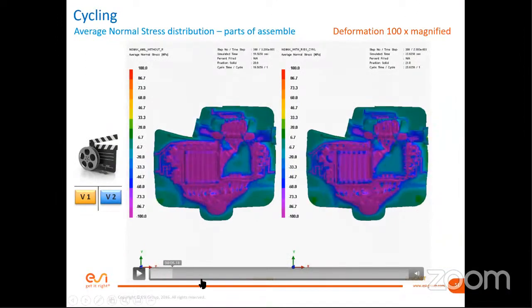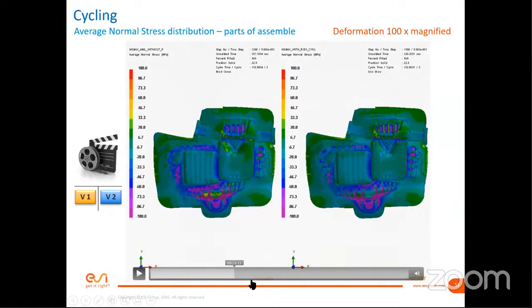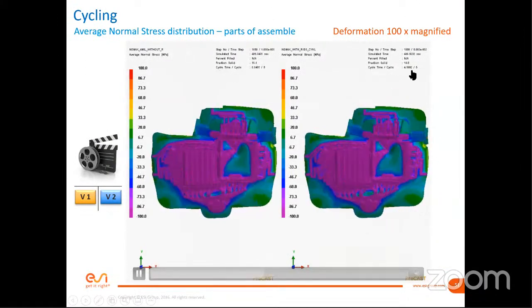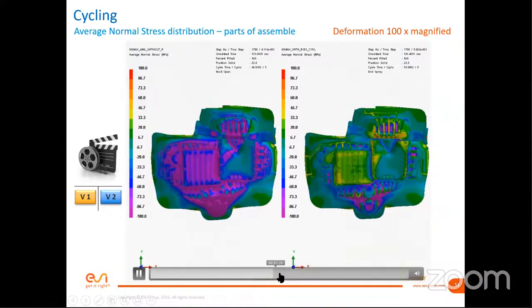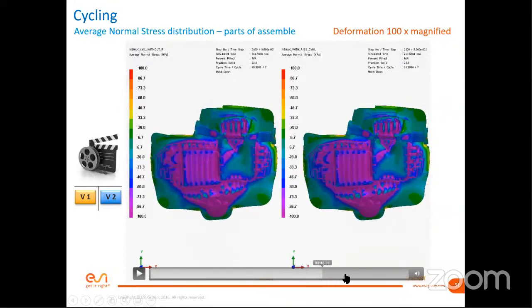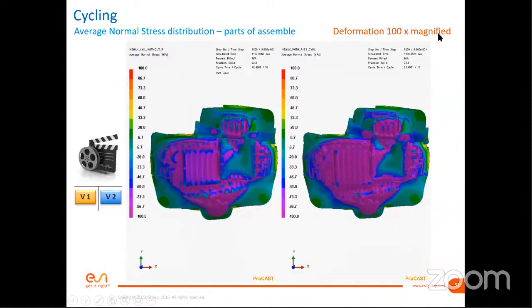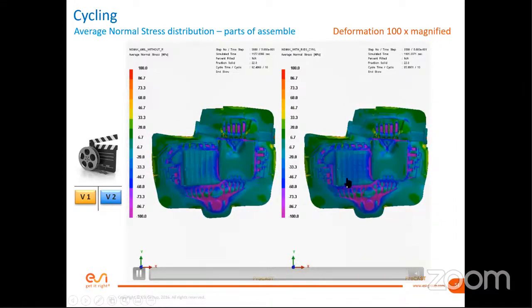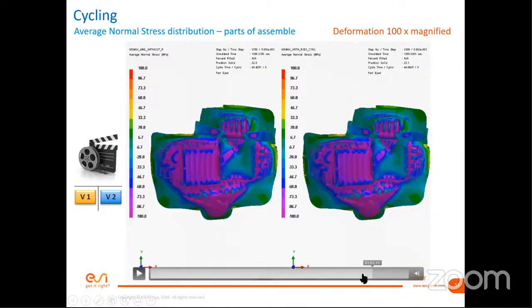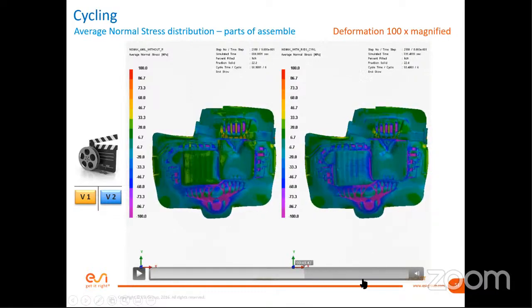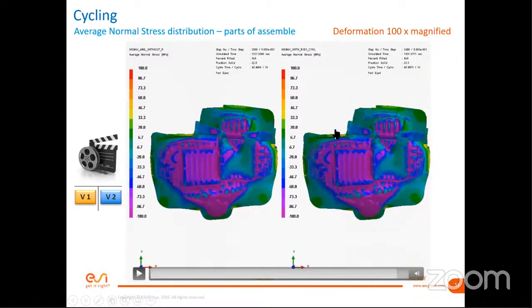And this cycling is presented here. You can see we are in the 5th cycle now, so you can see how many cycles are calculated. It's probably 10, and by 100 times magnified, you can see the thermal expansion of the die. So the die is really heated up, and it goes bigger because of the thermal expansion.